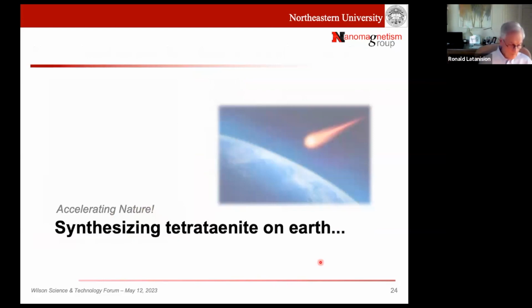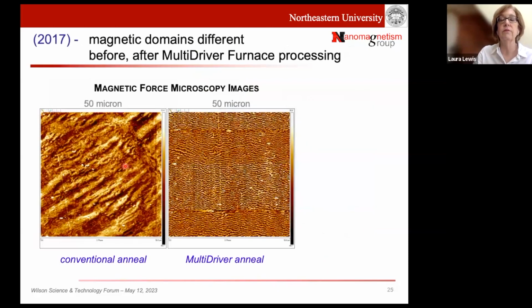So we're going to now go into our efforts on synthesizing tetrataenite on Earth. So here's, in about 2017, we had some samples, and these are bulk samples. We have bulk pieces of iron nickel, and we put them in our multi-driver furnace. And right away, you can see there's a very large difference between the conventional anneal, meaning we just cook them, and the multi-driver anneal, meaning that we put both magnetic field and strain on this material.